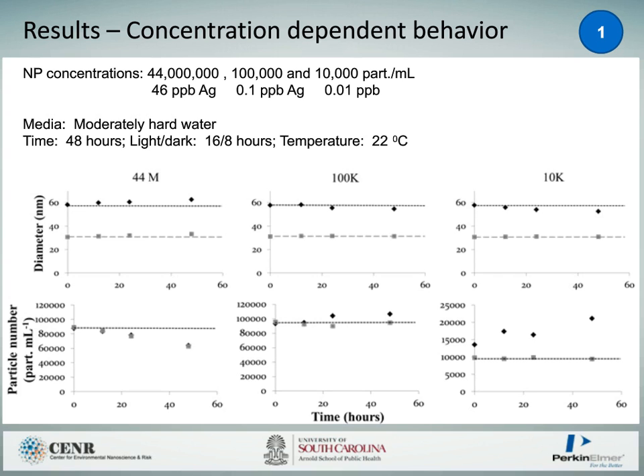So the media we used here was moderately hard water. We did a 48-hour exposure with a light-dark cycle of 16 to 8 hours at a temperature of 22 degrees. So if we look at the 44 million particles per mil solution, which are the graphs on the very left-hand side of this, we have a diameter and a particle number concentration.